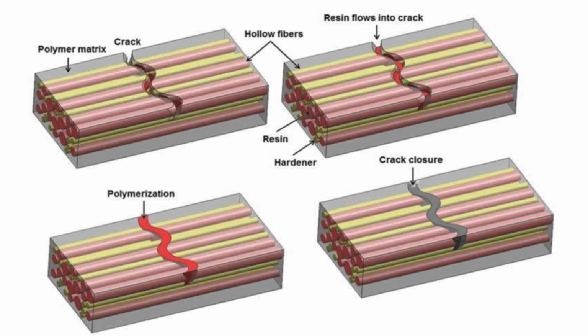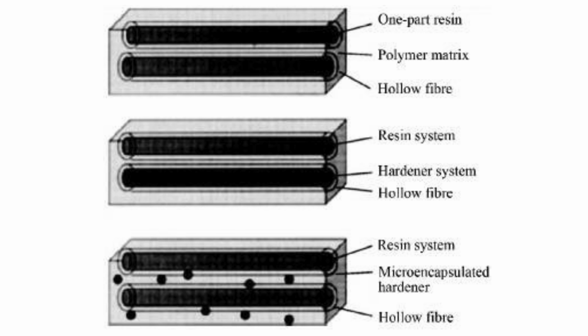The primary distinction between the hollow fiber type and the microcapsule type pertains to the configuration of the microcontainer. In the hollow fiber type, the healing agent is injected into the hollow fiber, which is prepared in advance. Subsequently, the hollow fiber is composited with the matrix post-treatment. The concept of hollow fiber-based self-healing materials was initially introduced by Dry's group, who proposed their storage within glass fiber tubes. The findings of the impact experiments demonstrated that the repair adhesive exhibited the capacity to migrate along the crack, in addition to facilitating the process of complete healing.